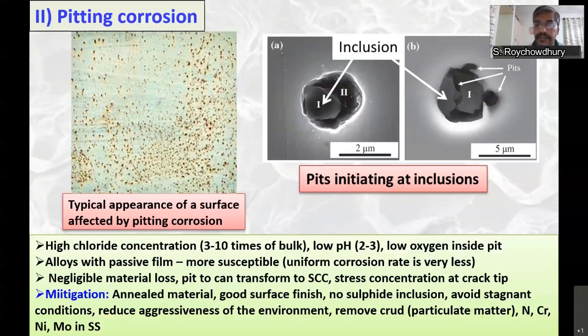It can also transform to other, more deleterious forms of corrosion like stress corrosion cracking. So mitigation: use annealed materials. If the material is strain hardened, if it is not properly annealed, it has a higher tendency to pit. Good surface finish improves the resistance to pitting corrosion. A rough surface will tend to pit more. No sulfide inclusions or oxide inclusions, as such inclusions act as preferred sites for pit initiation.